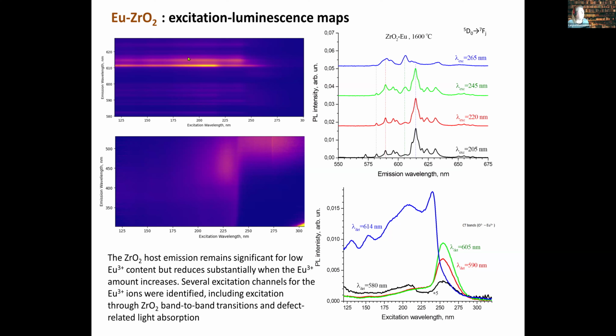And sure, we can excite these ions directly. And if we have a look at these two maps, we see that we have really very good emission of the host, exactly appearing between 200 nanometers and 300 nanometers in the excitation mode, and we have really good emission of europium ions.